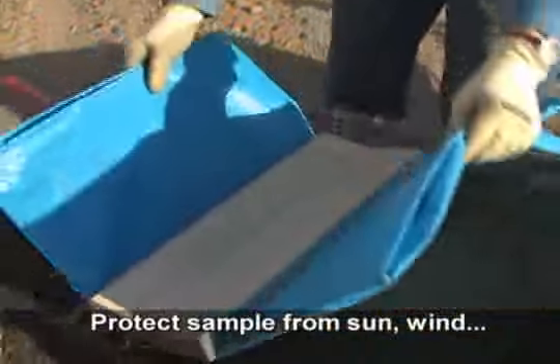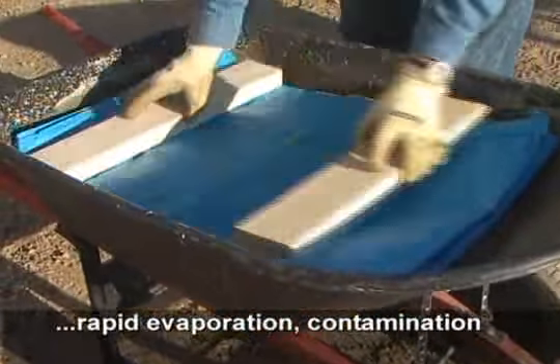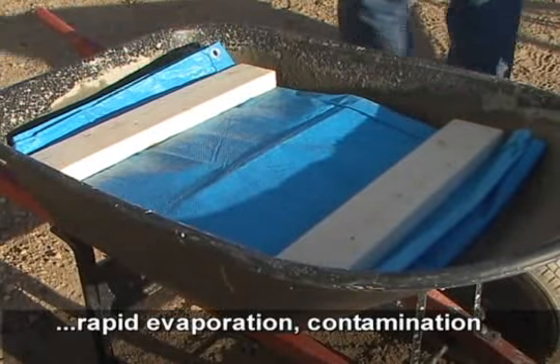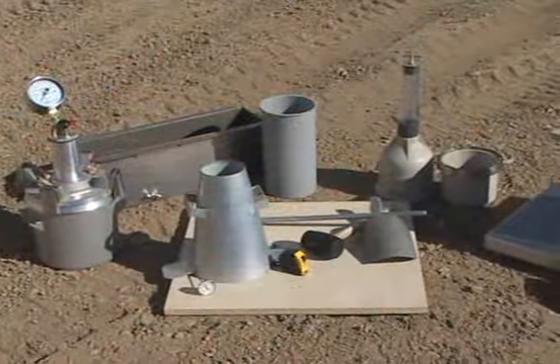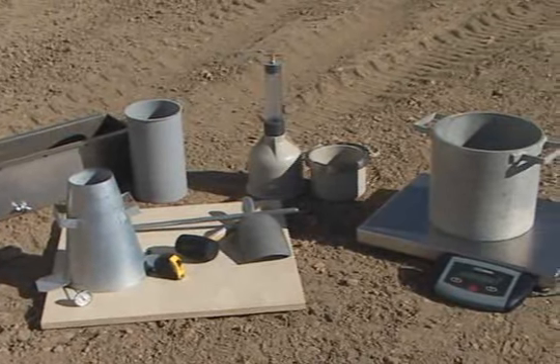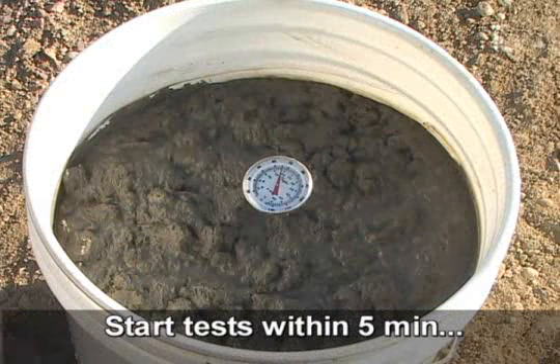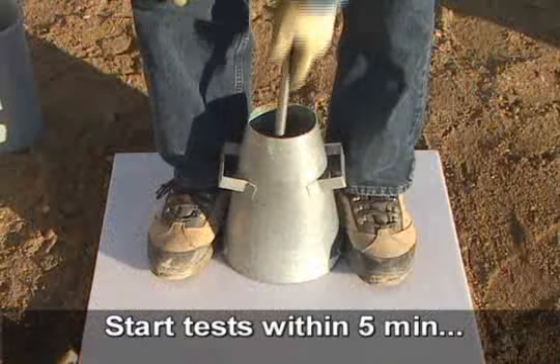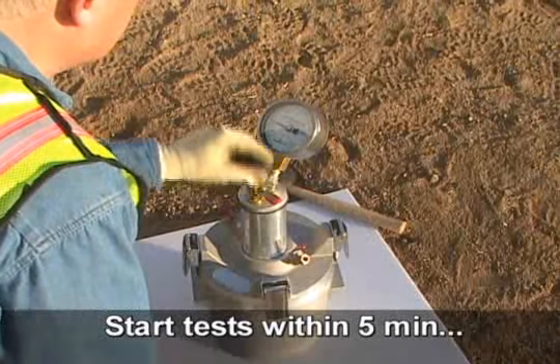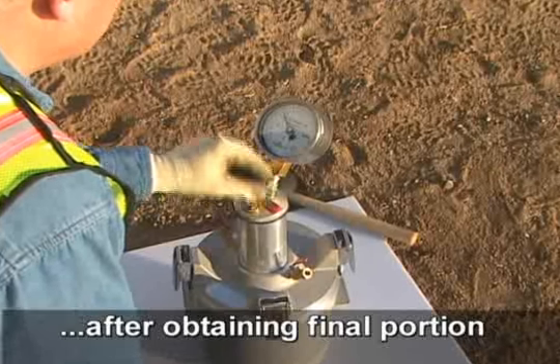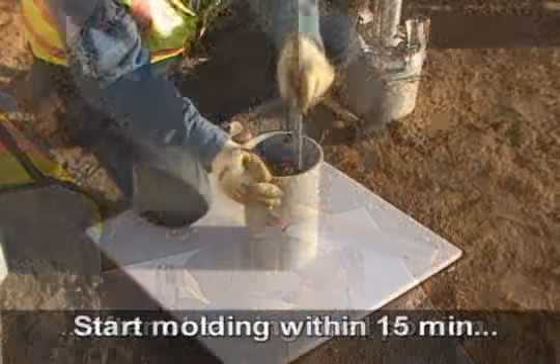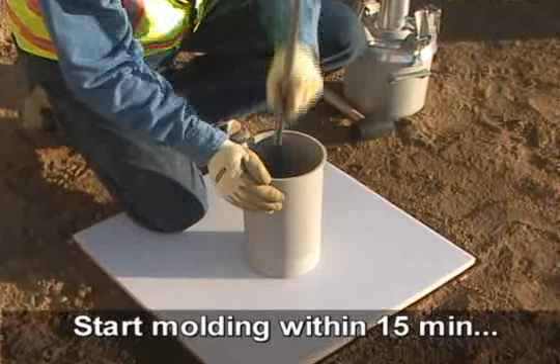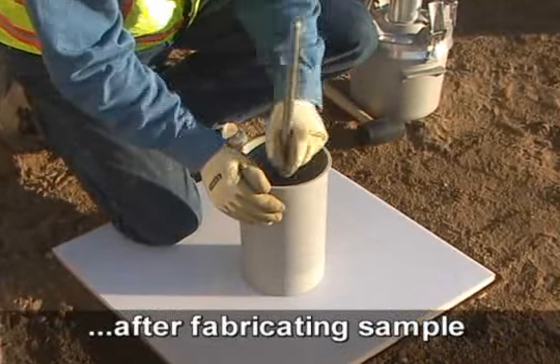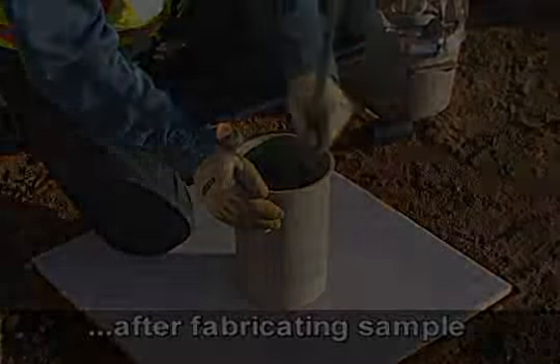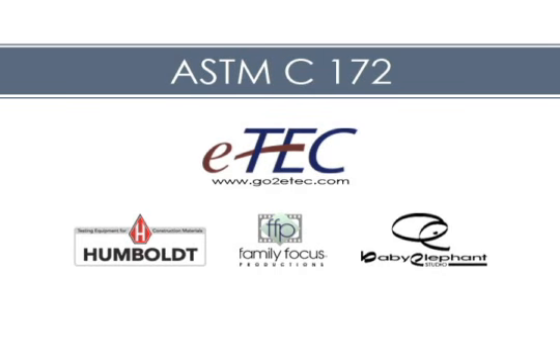While conducting tests on the fresh concrete, protect the sample from sun, wind, rapid evaporation, and contamination. All testing should be conducted without delay. Start the test for temperature, slump, and air content within 5 minutes after obtaining the final portion of the composite sample. Start molding strength test specimens within 15 minutes after fabricating the composite sample. Don't forget to clean your equipment.